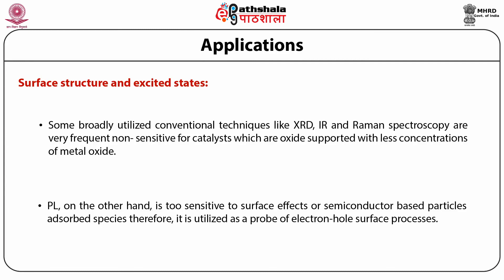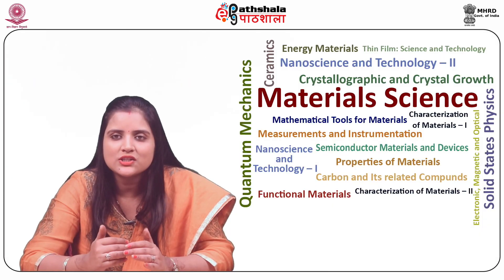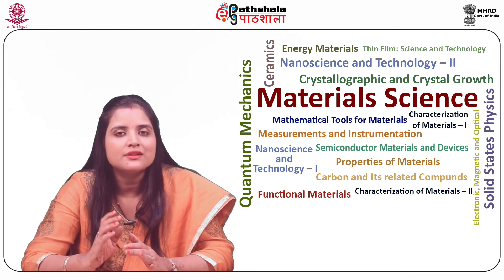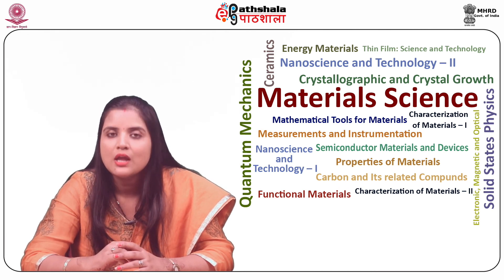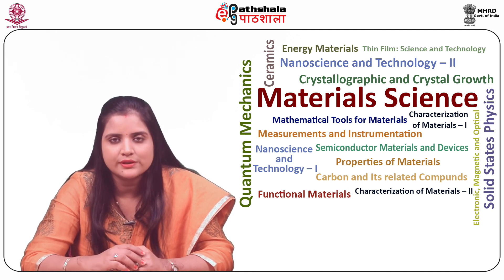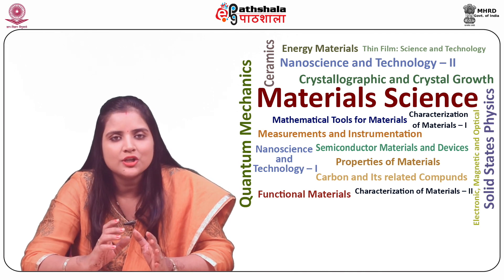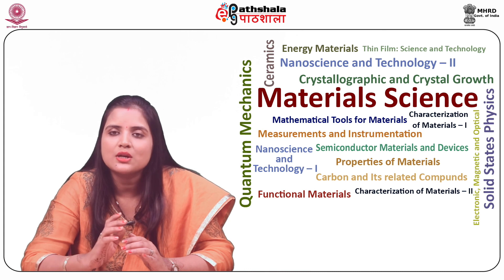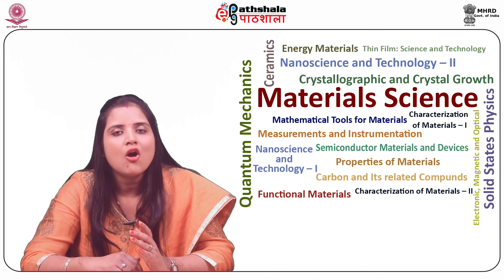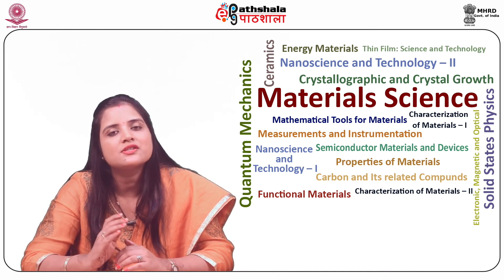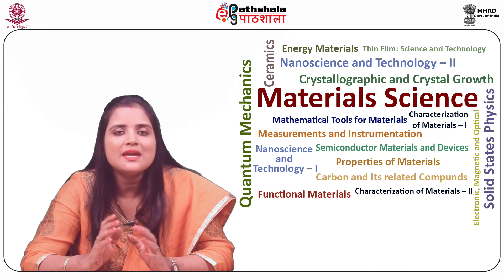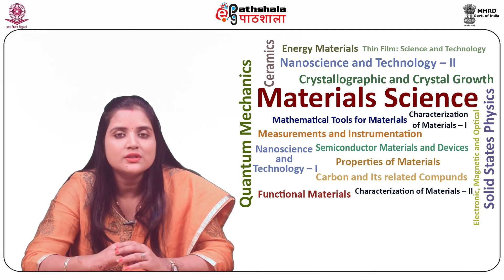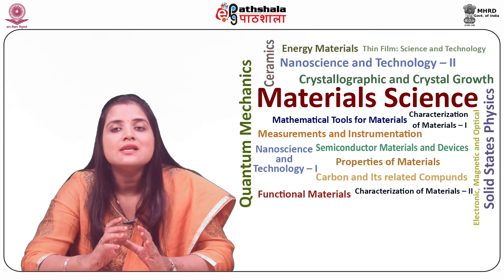We next study the photoluminescence spectroscopy limitations. In spite of the fact that this technique is not strictly quantitative in nature, it can be used to detect low concentrations of optical centers. The major scientific PL limitation is that several optical centers might possess numerous excited states that are vacant at low temperatures. Another major limitation of PL is that the luminescent signal can disappear. For example, in the PL characterization of silicon, no sharp line PL from 969 meV centers was observed when they had captured self-interstitials.